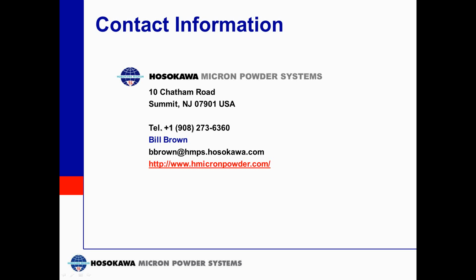Thank you. Next question. What is the expected life of a liner for an air classifier mill? Well, it depends on the type of contaminant or grit that's in the carbon black. We've seen on average liners and hammers lasting 6 to 8 months. Most of the time longer. There are some more abrasive grades where perhaps changing every 4 months, but let's say on average every 6 to 8 months for most of the slightly abrasive grades.